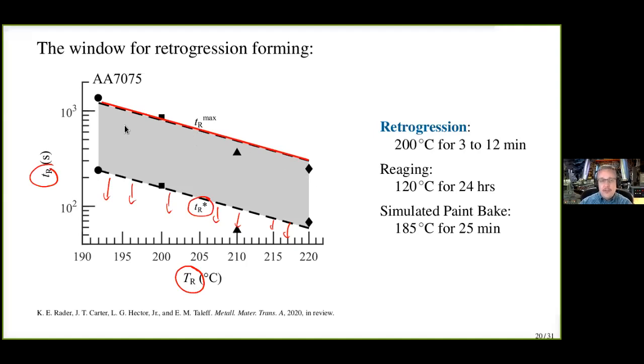So this tells us where we have to study mechanical deformation at warm temperatures. And that's the next step of our study, is now we know what times and temperatures we're allowed to work within. What are the mechanical behaviors at those times and temperatures? Okay, so from here, for retrogression, our recommendation is a temperature of about 200 degrees Celsius, because that gives us times from 3 to 12 minutes. Those times are reasonable for a forming operation. And that's what drove 200 degrees Celsius being a good target temperature.